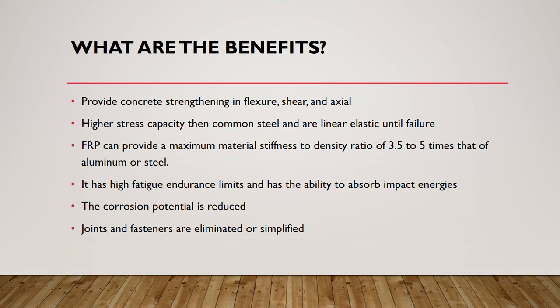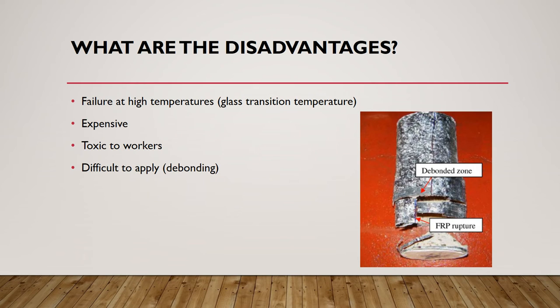FRP's non-corrosive nature aids in extending the lifetime of the structure and internal corrosion resistance is significantly increased. Another advantage of FRP is the heavy amount of research which aids in guiding various uses and application methods, and the materials and information are readily available to consumers. Among the extensive attributes of FRP, there are also disadvantages. This includes failure at glass transition temperature — when FRP composites reach this high temperature, the mechanical properties are significantly reduced as the material loses its hardness. Additionally, the resin used can be expensive as well as harmful to workers applying the material. Proper safety methods have to be implemented to reduce improper inhaling of chemical fumes. More disadvantages include difficult bonding between resin and substrate at low temperatures, and the material must be applied on dry surfaces, leading to application problems in very cold or high-precipitation regions.